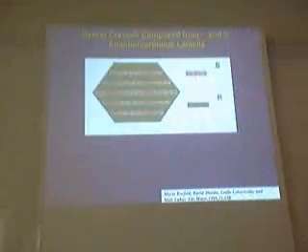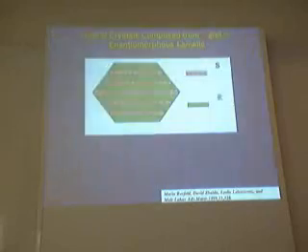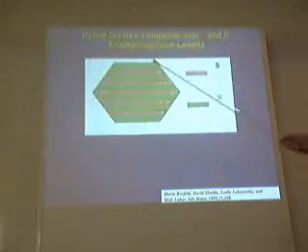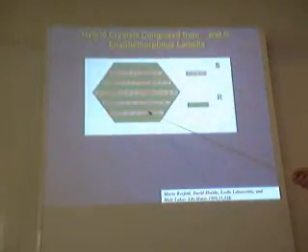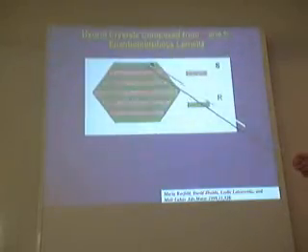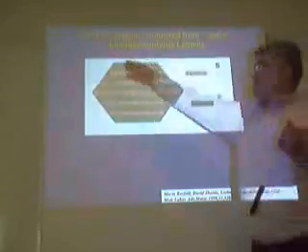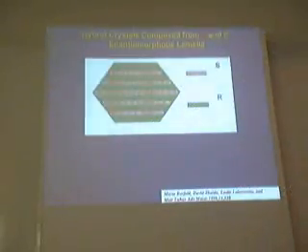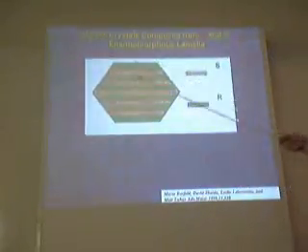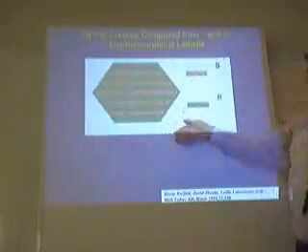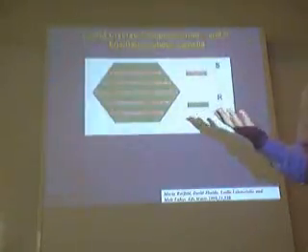When you take a single crystal and go to X-ray diffraction, you see a chiral space group. But if you take a single crystal, and again, we like very much to grind them, right? If you grind and then dissolve it, it has almost a racemic composition. But if you start grinding in this direction, you can find very high enantiomeric excess. And if you grind in the other direction, you don't observe an enantiomeric excess.